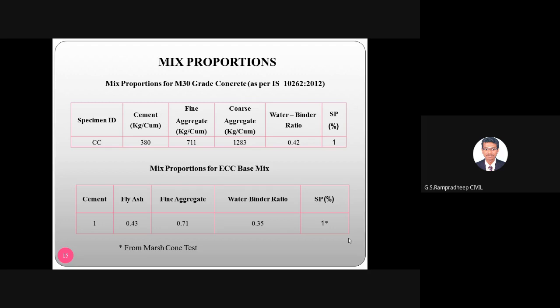And for the ECC based mix, what is the difference we are finding? We are finding only the removal of the coarse aggregate, right? If you mix the coarse aggregate, automatically the membrane height will be more, right? So here the coarse aggregate is not being used in the ECC. Instead, the ratio has been given clearly, 1 is to 0.43 is to 0.71 is to 0.35, right? And the percentage they are fixing as SP 1%.